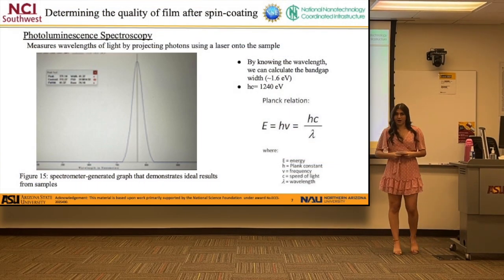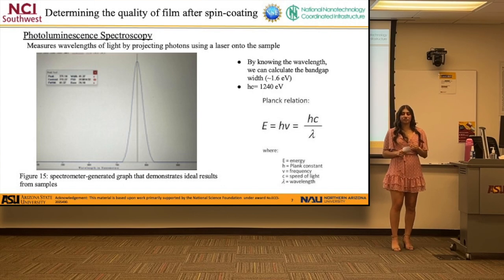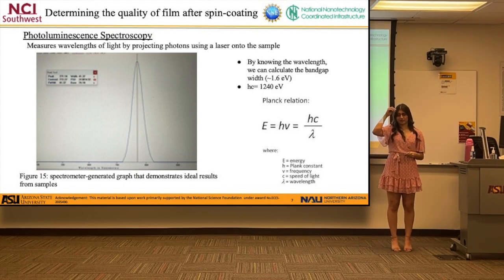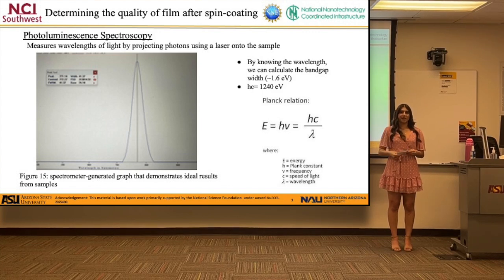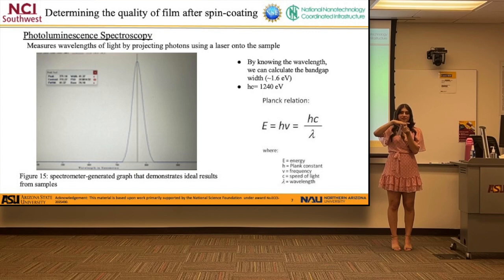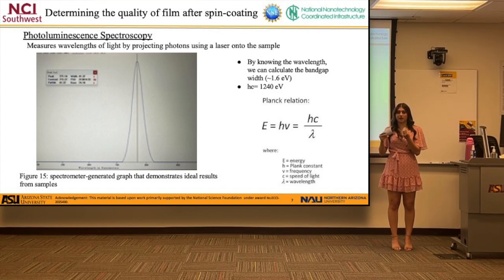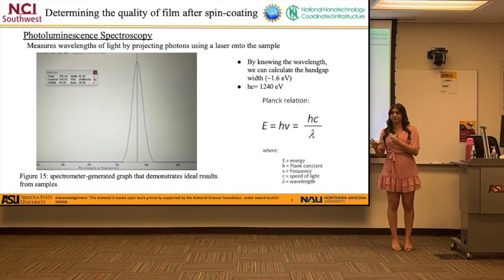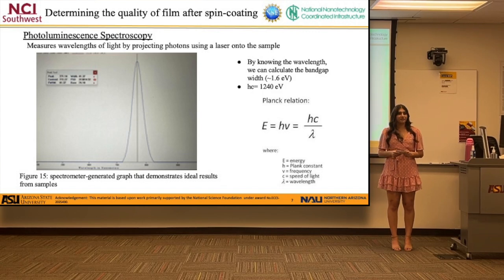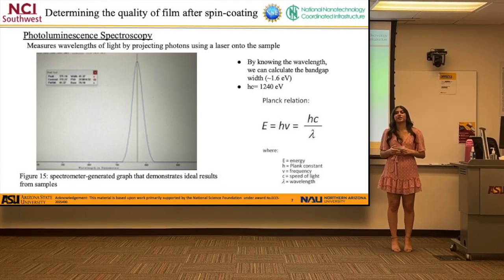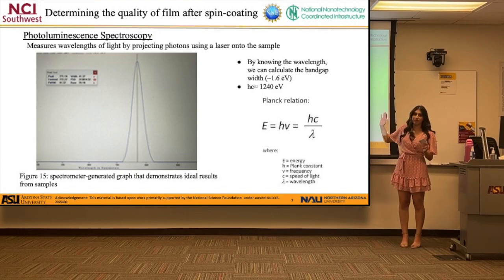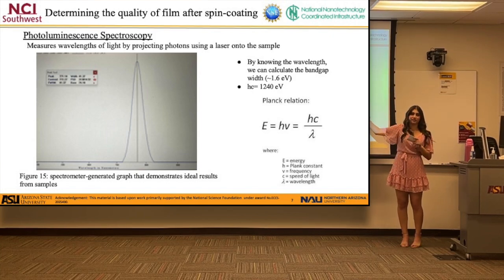I also ended up using photoluminescence spectroscopy. So essentially the way that this works is that it measures wavelengths of light by projecting a laser of photons onto a sample. And based off how much light was received back into a sensor on this device, it was able to generate a wavelength, which is essential because this way we can determine band gap width. And the relevance of the band gap width is because it determines the portion of the solar spectrum that a solar cell can absorb. And in order to calculate the band gap width, I use the Planck relation, which is a constant over the specific wavelength that the graph generated.